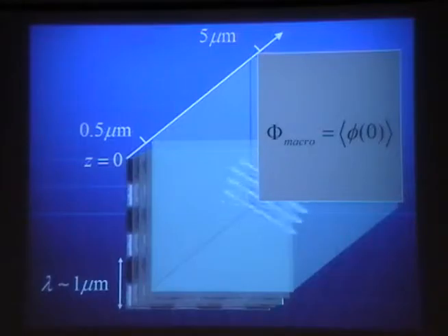Of course, as I mentioned, the elastic property is completely scalable, and if you reduce the periodicity by a factor of 2, this thickness is also reduced by a factor of 2. So it depends on how precisely you can do this business of patterning.